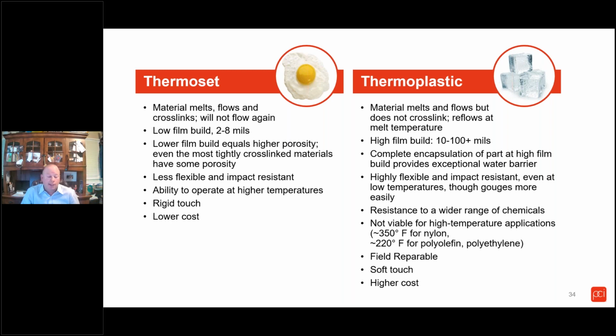Now, these coatings tend to be very flexible, very impact resistant, but they're not particularly hard coatings, so they will gouge. If they are breached down to the substrate, corrosion will tend to run more quickly once it's under, because they don't have the adhesion properties of thermosets.